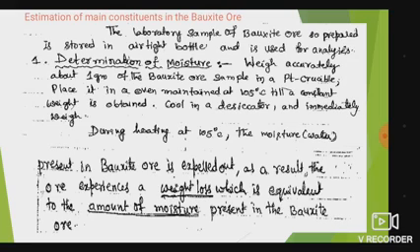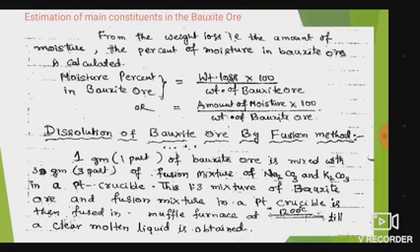It is a simple heating process. Moisture is expelled after heating the ore in the oven at about 105 degrees Celsius, and weighing it to a constant weight. If you get the constant weight, then take the weight and determine the weight loss before and after heating. The weight loss is nothing but the moisture content in the given bauxite ore.